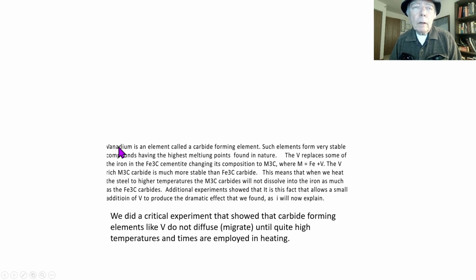What is it about vanadium that's going on here? Well, it's an element. The element vanadium has a symbol V. It forms a carbide, vanadium carbide. There are a bunch of elements similar to vanadium. They're called carbide forming elements. These elements form a very stable compound with carbon, very strong bond, which keeps them from melting to very high temperatures. Now, in steels, when you have vanadium present, it ends up in the iron carbide, and it replaces some of the iron in that, and changes it to M3C from Fe3C, where M is now a mixture of the 2 elements.